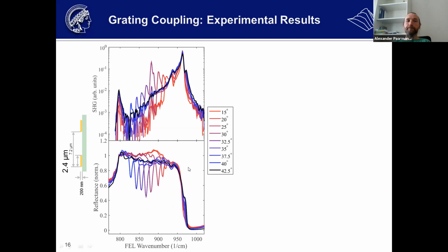So that works in principle, and now we look simultaneously at the second harmonic generation from these samples, and similar to the prism coupling, we see peaks that move with the resonance of the counter-propagating polaritons. We also see a bit of a peak at the forward-propagating mode. However, you see it on a logarithmic scale, but you also see that these substrate resonances that we just get from silicon carbide are still stronger. So it works, but it doesn't work that great.